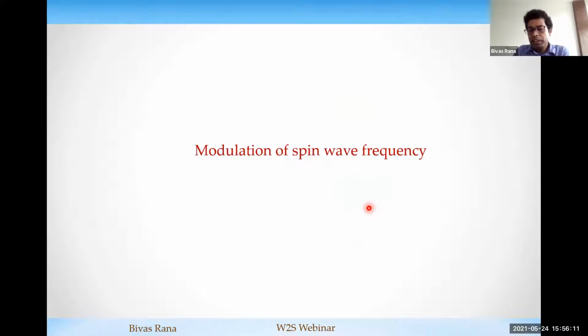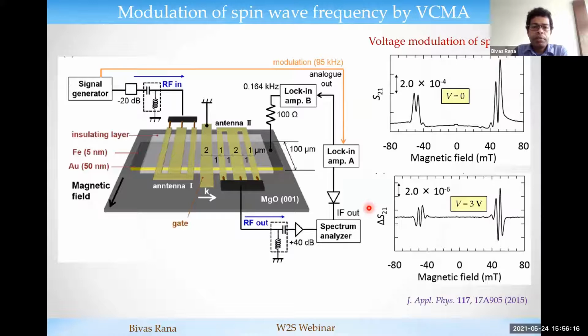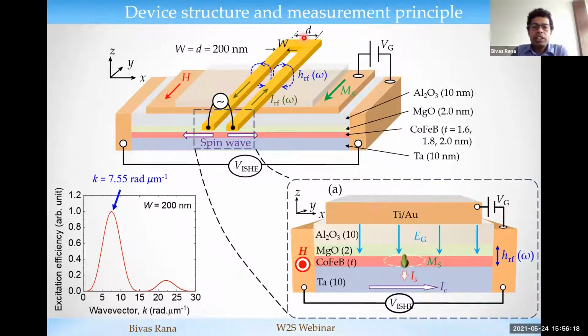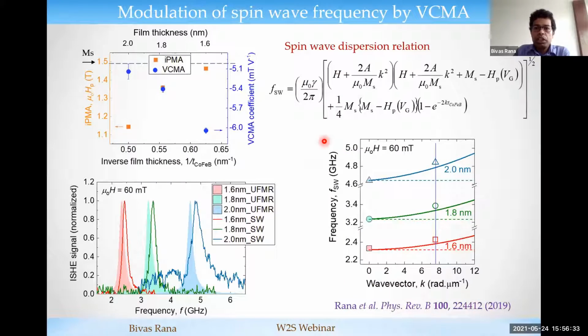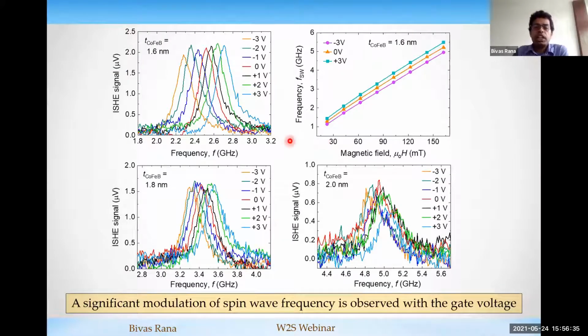Next, I investigated the modulation of the spin wave frequency. Basically, I tried to excite the spin wave with this antenna, and then by applying the gate voltage, we tried to see how much we can tune the frequency of the propagating spin wave. Coming directly to the result, I investigated cobalt iron boron film with 3 different thicknesses: 1.6 nanometer, 1.8 and 2 nanometer.